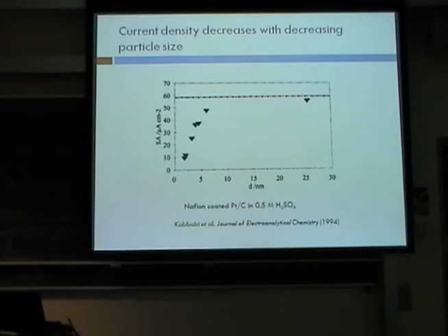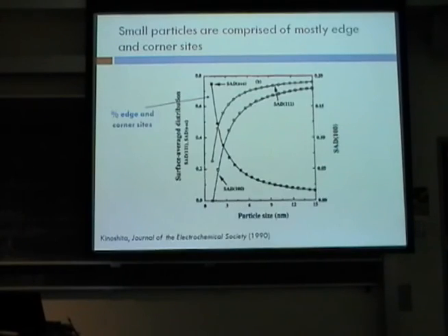One thing that's observed in the oxygen reduction reaction that's kind of unfortunate is that the fastest reaction rates on a per surface area basis occur on the biggest particles of platinum, the biggest crystallites on the surface. And that's a really bad thing from a cost perspective, because that means that you have lots of platinum atoms that aren't on the surface and are inside your bulk and therefore aren't able to participate in the reaction. So that makes it a very expensive catalyst. And the smaller particles that have a lot of the platinum atoms on the surface that you'd really like to use have a much slower rate associated with them.